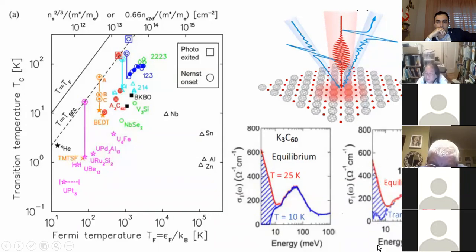Okay, so what is surprising in the discovery of this Cavalieri group in Germany is that if they excite the system by light, this phenomenon happens at very high temperature. The superconducting-like response can be observed, for example, at 100 Kelvin. This is 5 times higher than the actual known equilibrium transition temperature of this potassium C60. But they still see a very similar response to this superconducting response, with this missing Drude region.